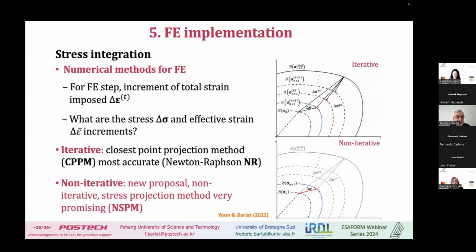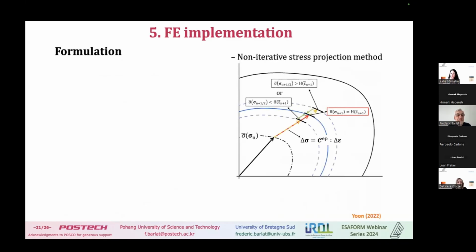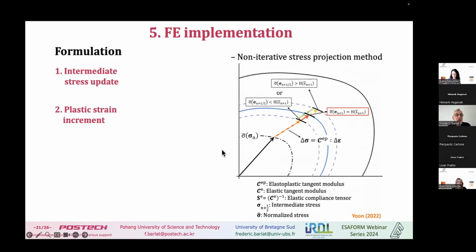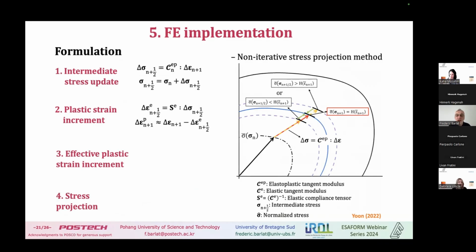No, it has been done in the past, and it was not always very used in the literature, and maybe one reason it was not that accurate. I'm not sure, but in this formulation, when we say it's non-iterative, we have to do a projection. So we first find an elastoplastic stress update, and the problem is when we do that, we are not exactly on the yield surface. So we have to do a projection on the yield surface to get exactly the loading point.